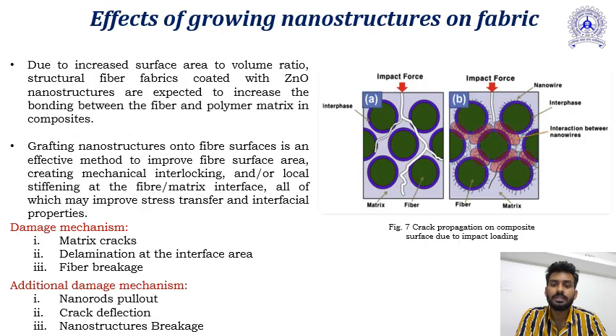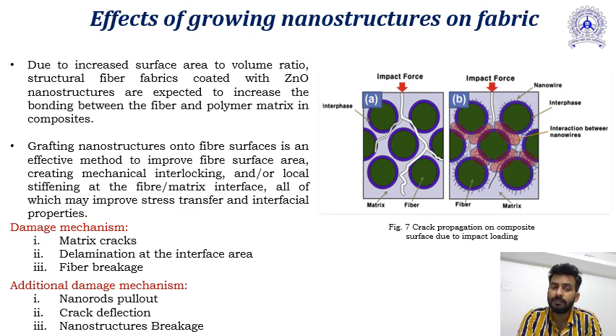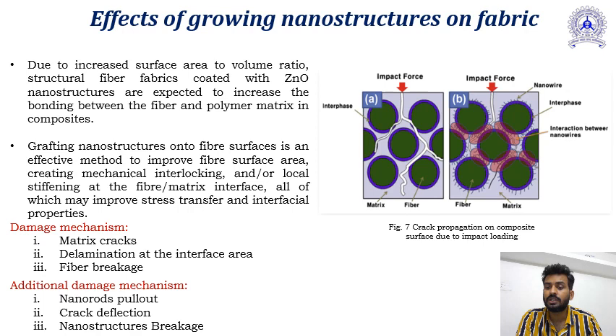Without nanostructure, the impact force causes basic damage. But when we grow the nanostructure, there is interfacial interaction between the different nanowires and the matrix and fiber, changing the damage mechanism. Initially the damage was only matrix crack, delamination at the interface area, and fiber breakage. With the nanostructure, additional damage mechanisms occur: nano rod pullout, crack deflection, and nanostructure breakage.